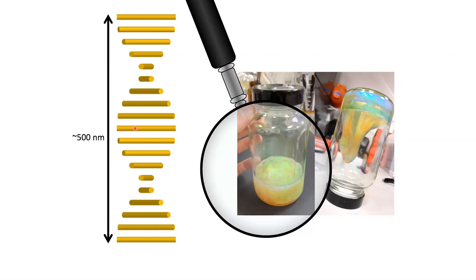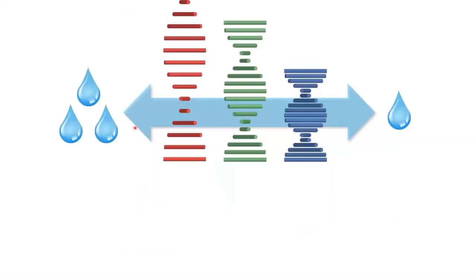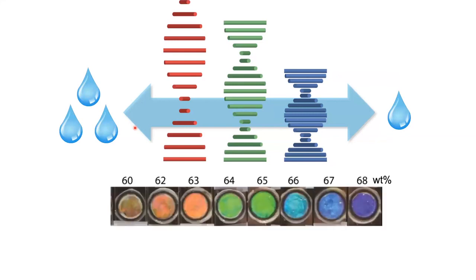And what is nice is that you can change the dimensionality of this phase by changing the level of water present in your film, the hydration. You can see here that you can tune the range of the color from the infrared to the ultraviolet light by simply changing the amount of water that you put. And this color is also particularly special. So we said that we change the water content: if you add water, the color becomes red shifted, so you are increasing what we call the chiral nematic structure.